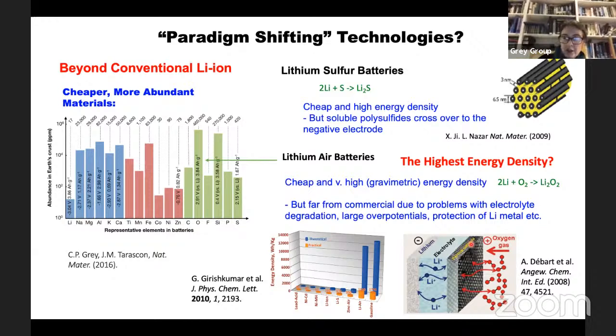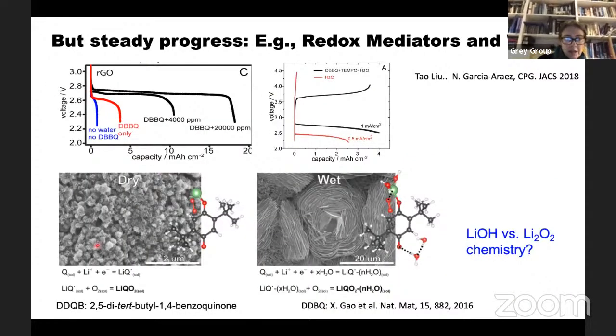The challenge, I'll show you in a pitch in a minute, is that you form these dense mats of lithium peroxide, and lithium peroxide is an insulator. So when you try to charge the material, it's very difficult to get the electrons into the material to oxidize the peroxide back to oxygen. And so there's a lot of work globally to try and solve this problem.